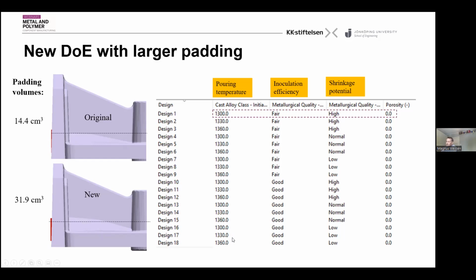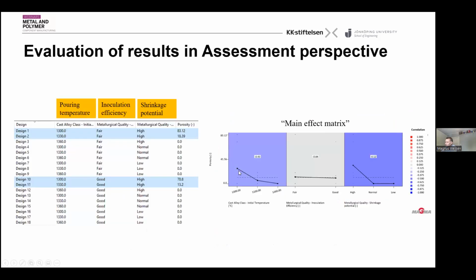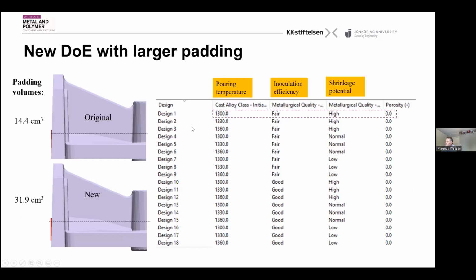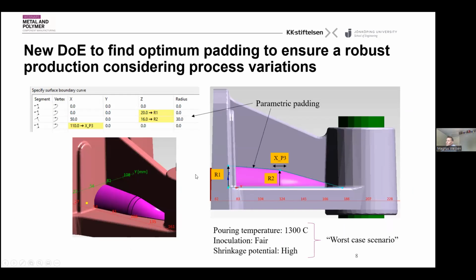Already at this stage, I actually could have drawn some conclusions. Instead of running all these 18, I could have made it even more simple, since I knew that the highest pouring temperature is good and the lowest pouring temperature was the bad one. So I could use this number and that number and that number. All these 3 settings would be enough just to try it out and to find if this is good enough. But now, of course, it shows that all my designs produce good parts. But there was an even smarter way.